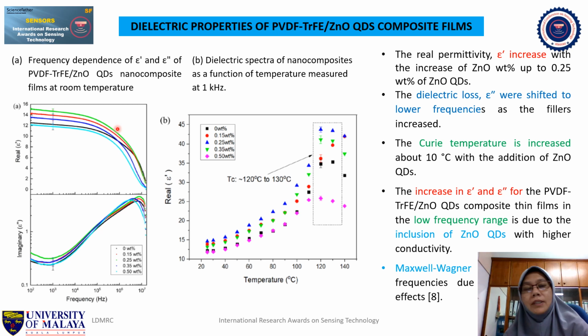The dielectric properties of this polymer nanocomposite study are shown in these two figures here. So these two figures indicate that the real permittivity increases as the composition of zinc oxide increases up to 0.25 weight percentage, and the dielectric loss shifted to a lower frequency as the fillers of zinc oxide quantum dot increase. And in this figure, we see that the Curie temperature increases about 10 degrees Celsius when the zinc oxide quantum dot is introduced into the polymer nanocomposite.